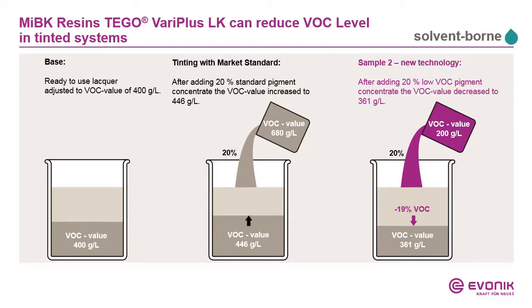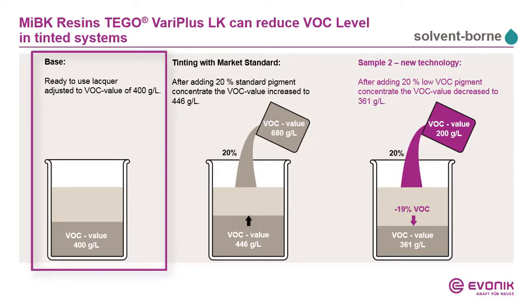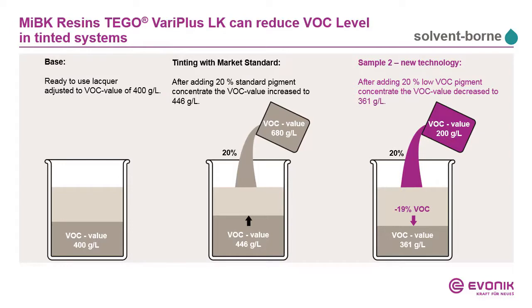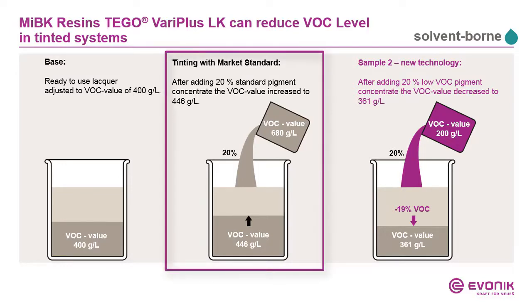How to explain it? Why do you use low VOC colorants? Keep in mind, you have a base. Let me start like this: the base paint has a VOC value of 400 grams per liter of VOC. Now you take this base and you tint it with a normal standard colorant. This standard colorant with organic pigments usually has a VOC value of about 700 grams per liter. So in this case, 680 grams per liter. And if it is a full shade, you use about 20% to get the right color.